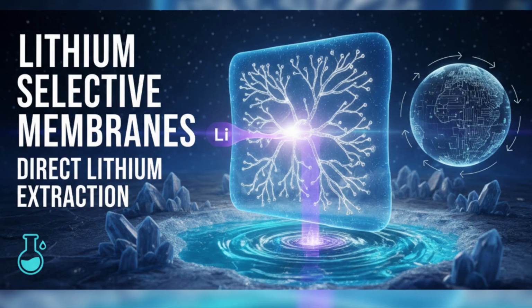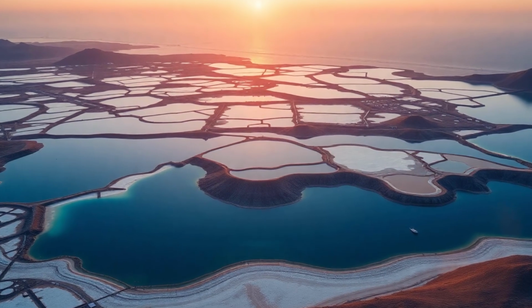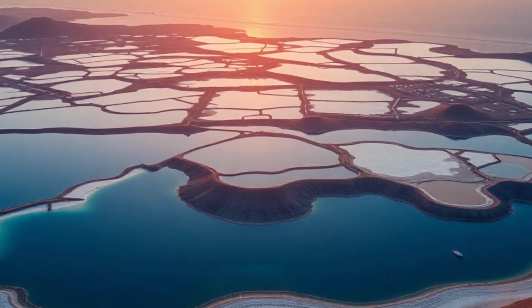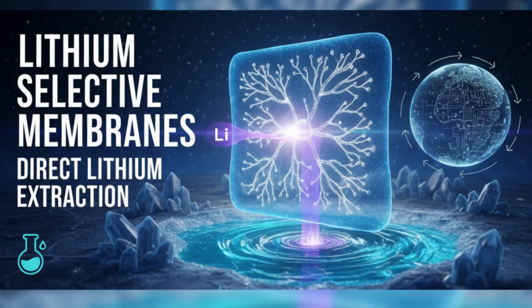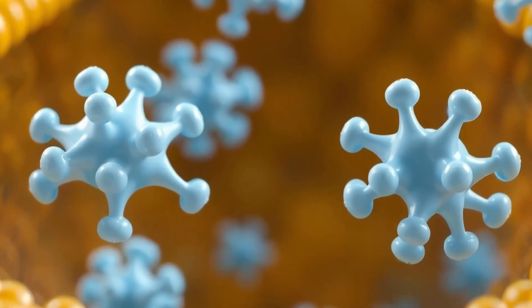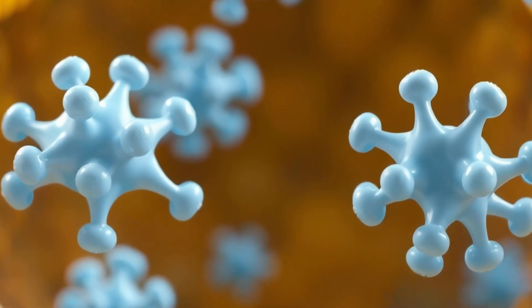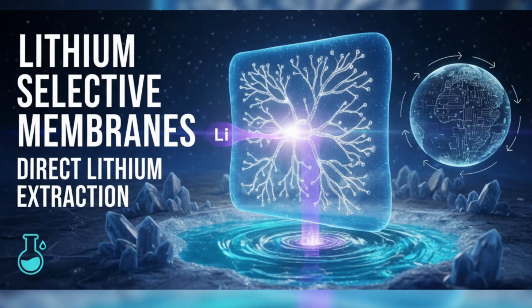All right, we've covered a lot of ground in this deep dive. We started with lithium, the white oil, saw its price skyrocket due to demand, forcing us to look beyond traditional sources, to things like low-grade brines and even seawater, with their unique challenges of low concentration and high competing ions. Which led us to lithium selective membranes. We explored the two main mechanisms: size sieving, exploiting the tiny bare Li+ ion, using rigid inorganic structures like ISEs, which offer incredible selectivity but are brittle and hard to make, and binding affinity, using chemical attraction with organic molecules like TBP or crown ethers in more flexible polymer membranes, which are easier to process, but generally have lower selectivity and potential stability issues.